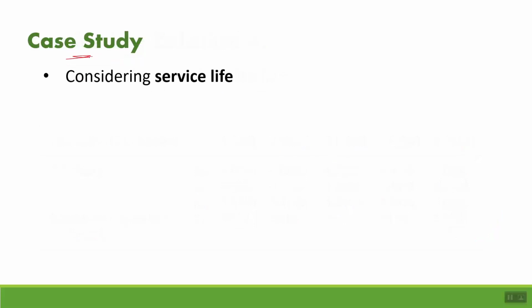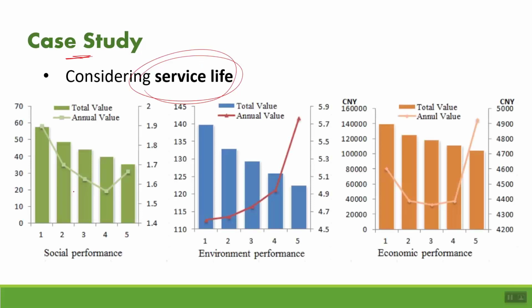When the same case study is considered, but with considering the service life, we can see that by increasing the replacement percentage of the fly ash in the concrete, at first the environmental impact is very high. Then it's reduced by increasing the fly ash up till a specific point, which represents the 40% replacement ratio. Then it increases again. Then the optimal replacement percentage for the environmental performance is 40%.